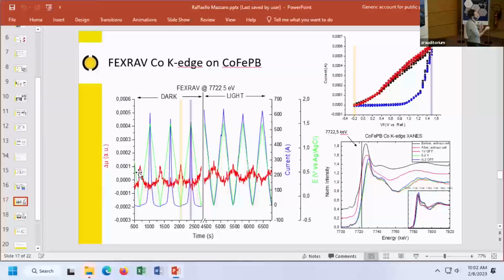So you see that we see these bumps here corresponding to the minimum potential, minus 0.2, where we have the reduction of the cobalt 3 to cobalt 2, and that is something we expected. But we also see that upon illumination, in light condition, in the case of cobalt iron Prussian blue, these peaks are broadening. So we have a larger potential window where we are decreasing the oxidation state of cobalt. That is something that is fully related to the light in our system. And this is repeated multiple times, and we see the same signal.